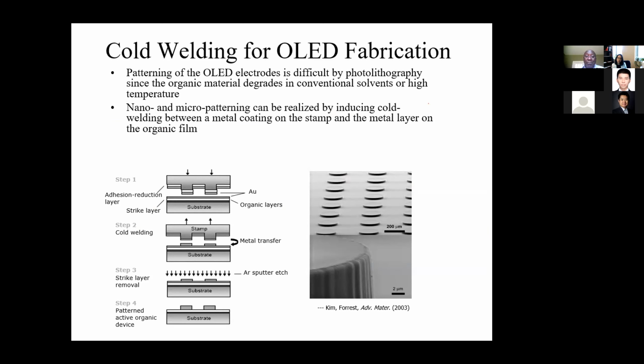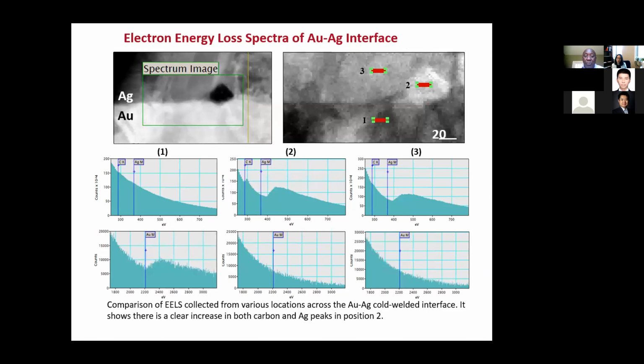But they found that when they applied too much pressure to the stamps, the screens were damaged. And when they applied too little pressure to the stamps, then you didn't have adequate adhesion. And so what we did was to try to understand this. And we imagined in the early days that there are defects, impurities between the stamp and the substrate. So the nature of the contact is affected by the presence of these defects.